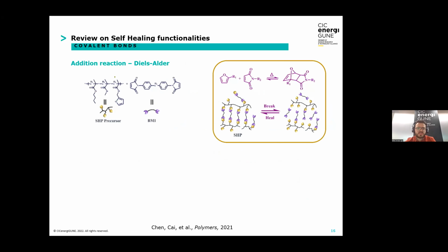And finally, the last example would be the addition reaction, which is particularly suitable also for polymer electrolytes since it functions well with hydrophobic polymeric materials. It is sufficiently reversible through the application of temperature for its activation, and self-healing is induced through a partial depolymerization, which occurs at the fracture site and reforms the moieties needed for the healing. The most representative example is the Diels-Alder click reaction, as we can observe in the example. A conjugated diene and a substituted electron attractor alkene react to form a substituted cyclohexene, which functions as bridge between two polymer matrices. This one is easy to break under rupture, but can easily recover and heal after increasing the temperature to 60 or 70 degrees, where a retro Diels-Alder reaction occurs, producing a number of functional groups that under cooling may react and reform the broken bonds.